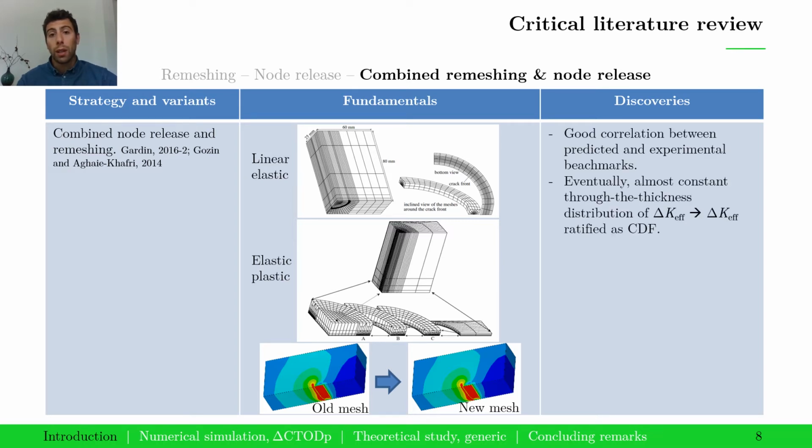According to this strategy, the predicted crack shapes have been observed to correlate well with experimental benchmarks, and it has been discovered that an almost constant through-the-thickness distribution of delta K effective is reached, what according to Gardin permits to ratify delta K effective as the true crack driving force.